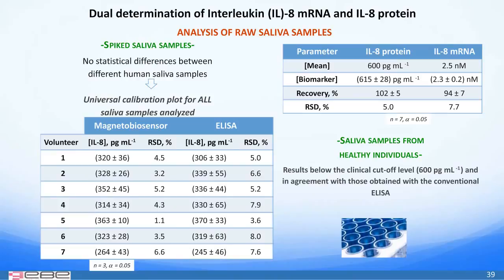The results obtained in the analysis of spiked samples confirm the reliability of the methodology to determine low concentrations of both biomarkers in raw saliva following a simple working protocol. Regarding the determination of the endogenous content of protein in saliva samples, the obtained results were statistically in agreement with those provided by a commercial ELISA kit and, as expected from samples collected from healthy volunteers, below the commonly accepted cutoff value.